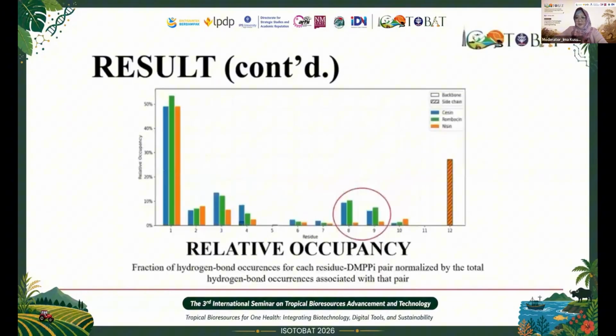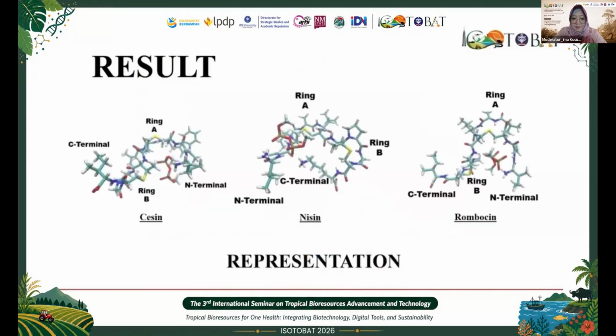From the occupancy analysis, we can see different binding trends. Cesin and Rombocin interact primarily at ring A and are supported by ring B to maintain the presence of the MPPI, while nisin is supported by the side chain of residue 12 to maintain the presence of the MPPI. Here, we use relative occupancy analysis because the binding frames between nisin variants and the MPPI are very low, only about 10% of the total trajectory. This is the representation of the binding.